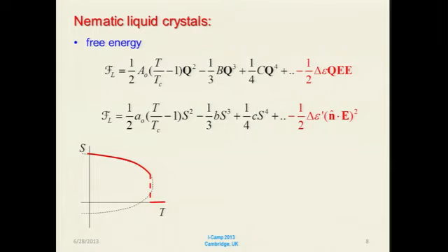The effect of an external field is important. An external field comes in like this. So this is coming from the expression for the energy density I showed you before. And in terms of the director, we have this coupling. And if delta epsilon is positive, the material wants to line up with the electric field. So essentially, all displays are based on this term. Now, there's two things that are worth pointing out.